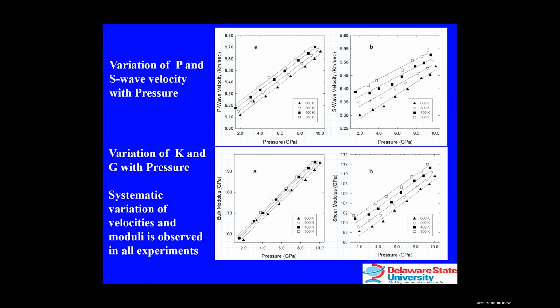This is also the case for the P wave and S wave velocity plotted as a function of pressure in the top two diagrams, and for K and G plotted in the lower diagrams. We see that in all cases, the velocity and the moduli all increase linearly and systematically with pressure. We have carried out measurements on several different samples, maybe 4 or 5 sample compositions, and we see this behavior in all the samples.